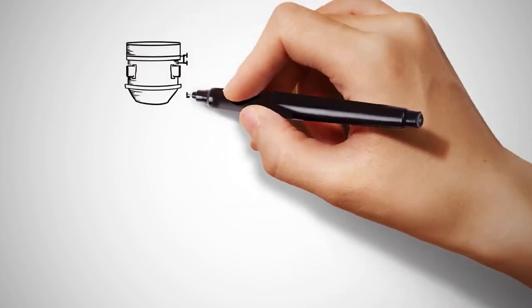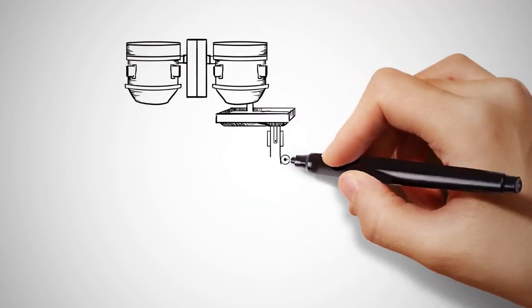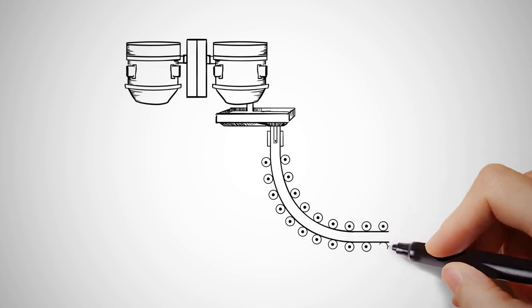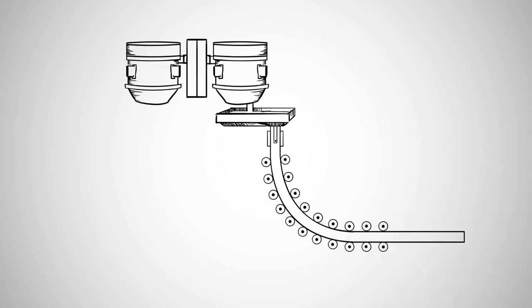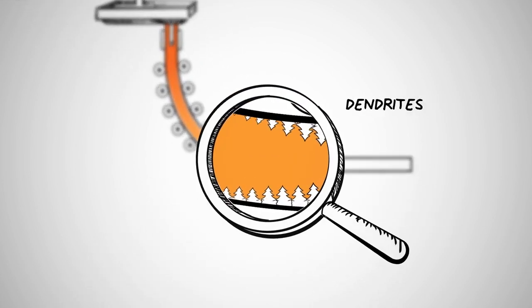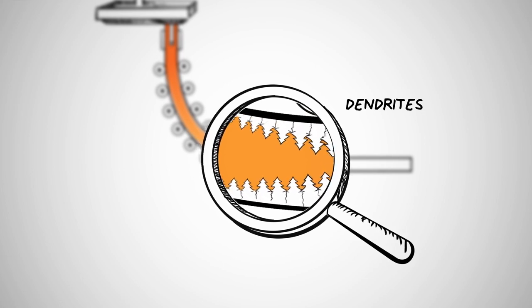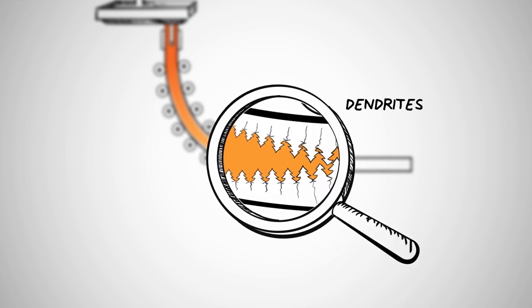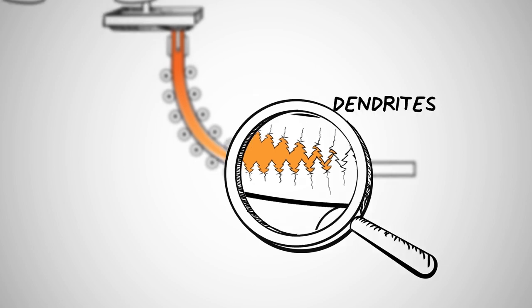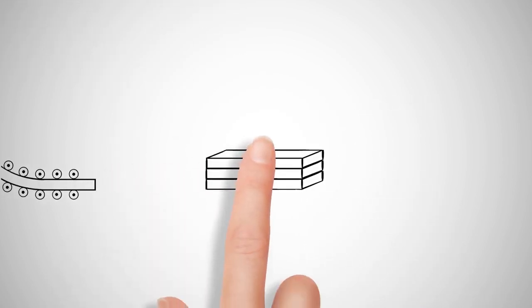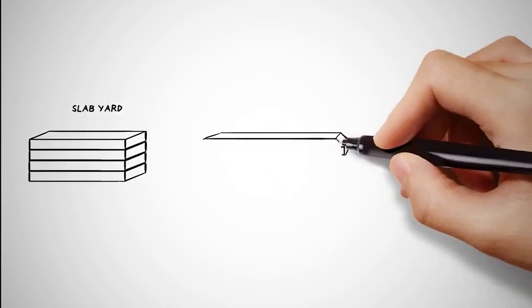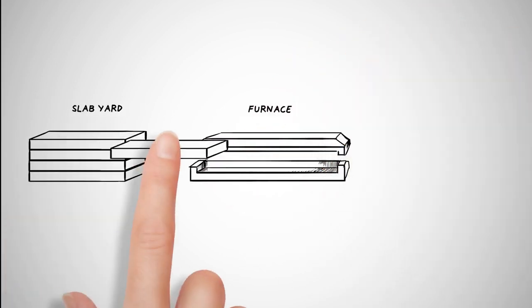Liquid steel is either produced from pig iron in a converter melt shop, or scrap is melted in an electric arc furnace. During casting, the steel starts to solidify from the outside to the center, and crystals grow in tree-like shapes. The so-called dendrites then gradually consume all the liquid that remains between the tops of these trees and their branches. In the conventional process, the cast slabs are stored in a slab yard where they cool down. They are then reheated for rolling.